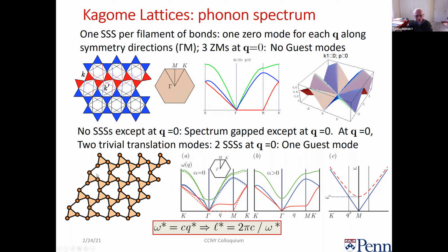Now let's look at this thing where I have twisted it. I have now lost all of the straight lines which allow the system to have a state of self-stress. I no longer have any states of self-stress except those having to do with the whole sample. And so I no longer have a number of zero modes equal to the number of states of self-stress. So this lattice, which had zero modes, when I twist it, gets its phonon spectrum lifted to a finite value. The bulk phonon spectrum of this lattice, which looks floppy as all get out, is actually gapped everywhere. So I went from having a V-shaped spectrum, that's this blue line, to, when I twist it, this red spectrum.